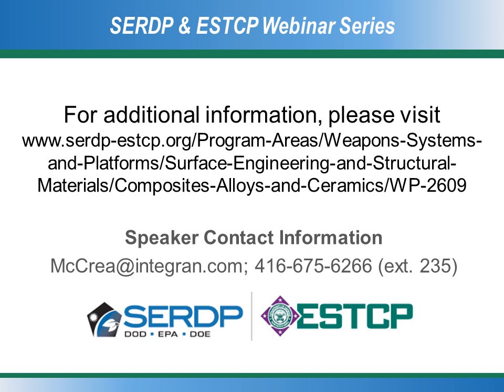Yeah, I would say the main area that we've seen the biggest uptake, chrome is a good coating, and it's been used a number of places, and it's very hard to change somebody's use of a material unless they're forced to. But in areas where there's actually a process and cost benefit has been in areas where there's use of hydraulic cylinders in chloride environments.